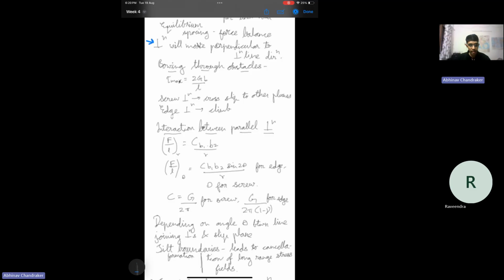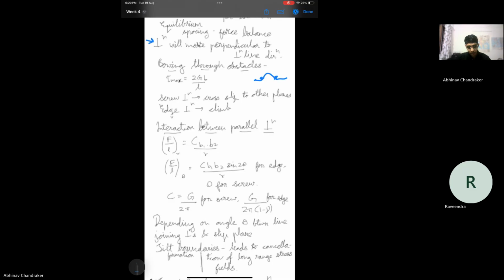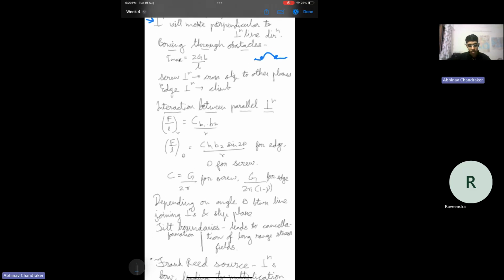And in order to keep on gliding, since there's a shear stress being applied when loaded, it will try to keep on gliding. It might many times have to bow around the obstacle, bow through the obstacles. For example, if it's pinned in two places, it will try to bow around. And the force which is required for the bowing to be successful. So once it bows around, it can form a kind of loop and then break away from the original dislocation, form a new dislocation, and keep moving. So sir has shown the steps of the bowing, the breaking off as a new dislocation, and the continued movement. So you can see that in his lecture.